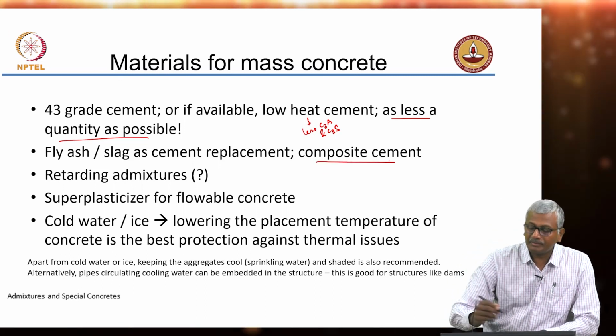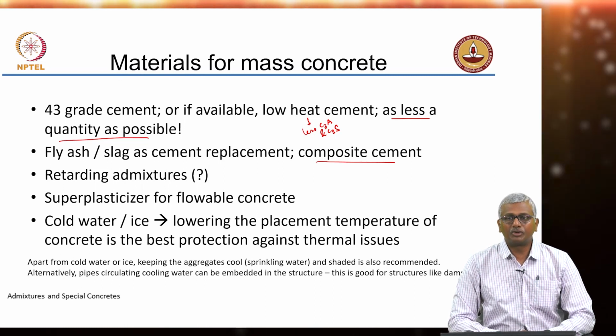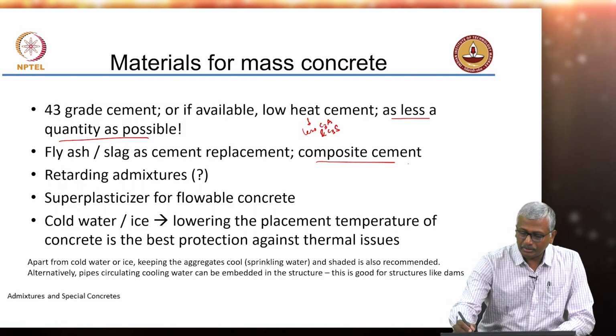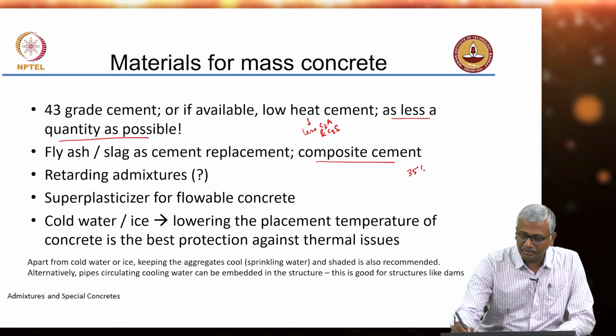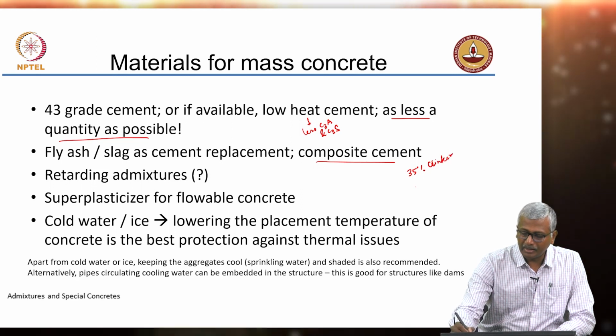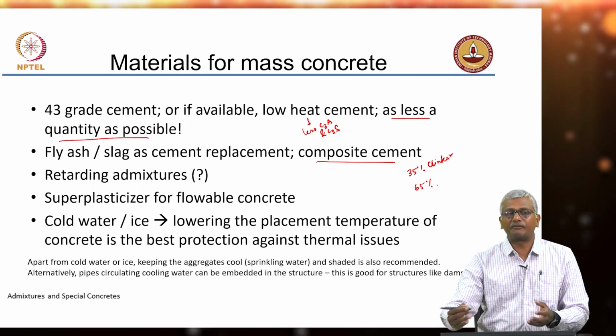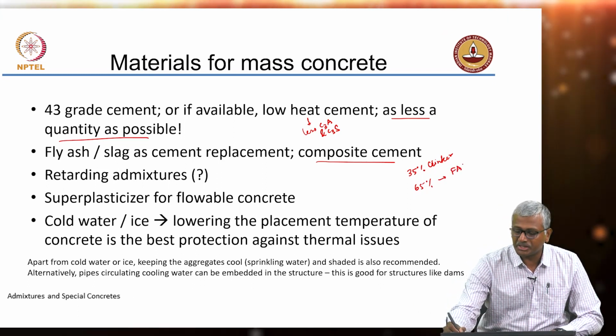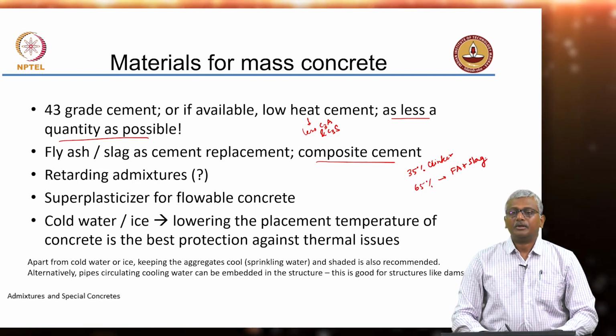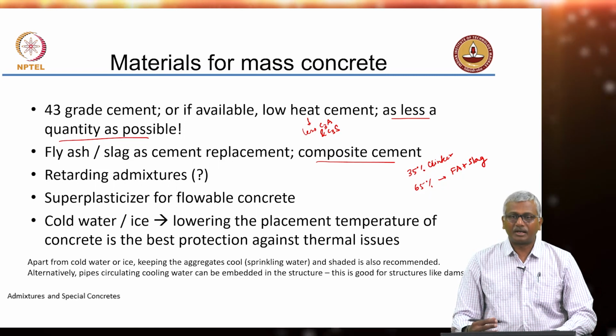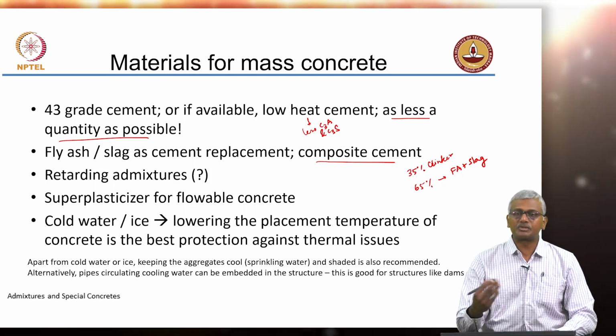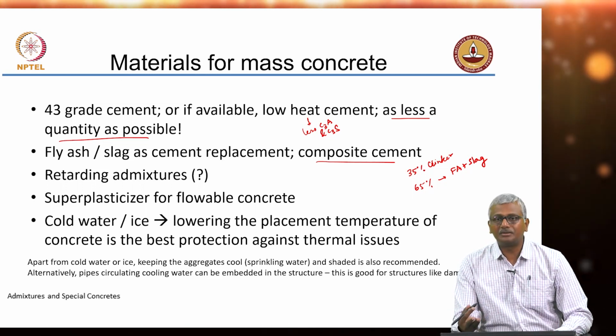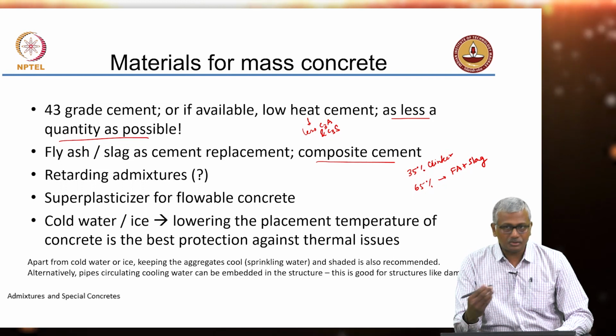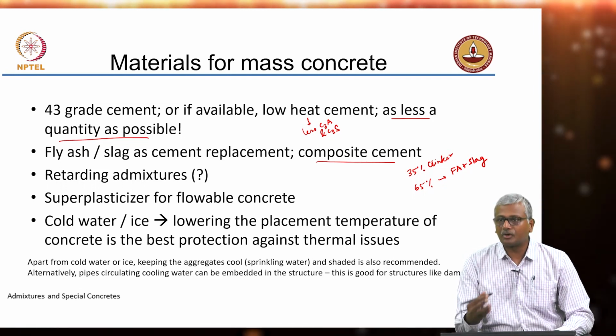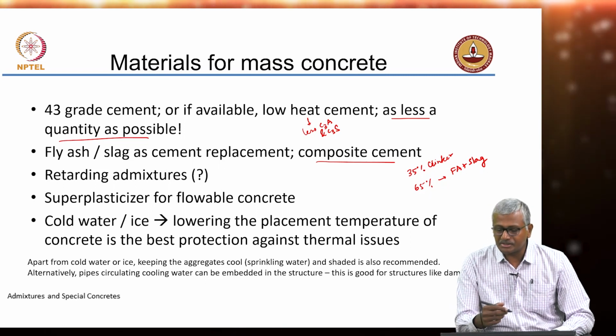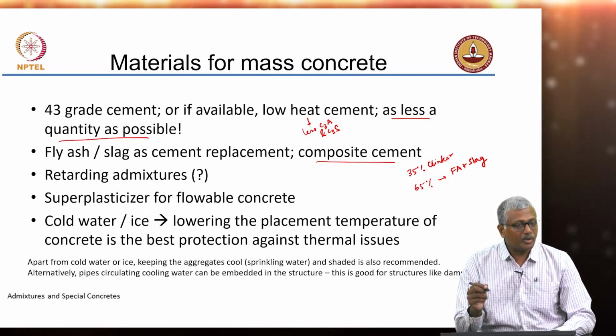And of course, today you also have the potential of using composite cement. If you look at the IS composite cement standard, it talks about a cement which has only about 35% clinker and remaining 65%, of course, you also have to have gypsum. The remaining 65% is a mixture of fly ash and slag. Very soon, composite cement standard will also include limestone calcined clay cement, but of course, you will not be able to use limestone calcined clay cement in applications which need reduction in heat, because LC3 does not really cause a major reduction in heat. It will cause some reduction, but not a major reduction. Okay. But fly ash and slag at high replacement levels can definitely lead to very good heat reduction.